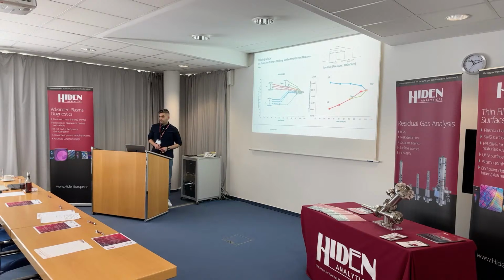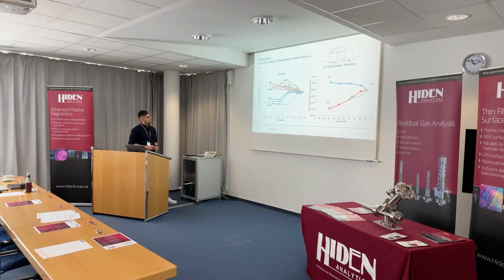So here are different pulsing modes: ion flux and ion energy of different pulsing modes for different duty cycles. As we increase the duty cycle to the continuous wave, we see HF pulsing decreases in ion energy, LF pulsing ion energy increases when we go to higher duty cycles, and the sync pulsing decreases. And this is for different pressures.